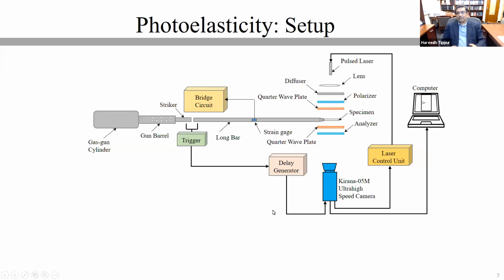First, I will show you some photoelastic results so that you appreciate the difficulties that we faced. Here is an experimental setup with a gas gun. The gas gun basically launches a striker. The striker impacts this long bar, and that in turn loads the specimen. The specimen is kept as part of a circular polariscope, a standard circular polariscope.